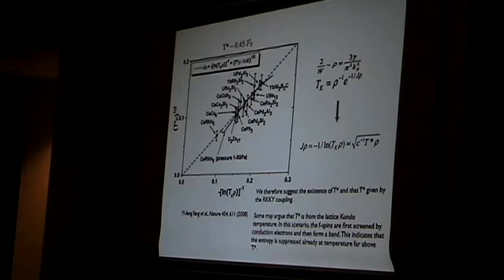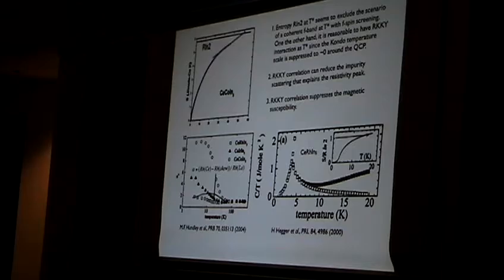This seems to suggest that T* is given by the RKKY interaction. That's a very interesting point because previous theory actually saw T* as some kind of lattice Kondo temperature. In that scenario, if my understanding is correct, you actually have 4f spins which are first screened by conduction electrons and they form a band. However, this indicates that the 4f doublet is preserved already at temperatures far above T*. What we really find experimentally for the entropy of CeCoIn5 is it goes to R-log-2 value for the ground state doublet at about 50 Kelvin.